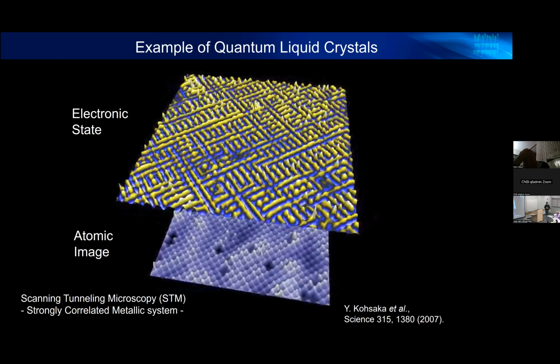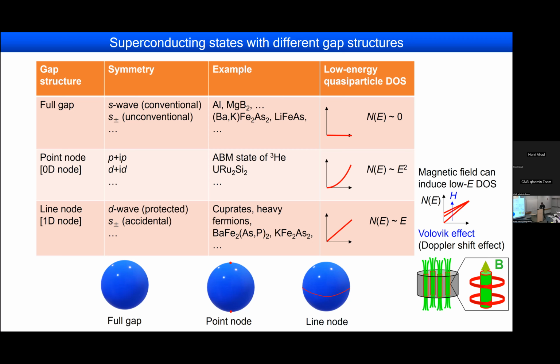Let me start with the general classification of the superconducting gap structure. I think you know very well that you can have a fully gapped state, and you can have point nodes or line nodes in the superconducting gap. If you have such a nodal superconducting state and apply a magnetic field, you can have vortices, and around them a supercurrent going like this. Then you can induce low energy states, which is called the Volovik effect. This has been around and is well known.